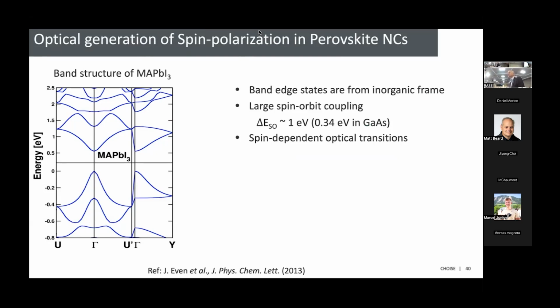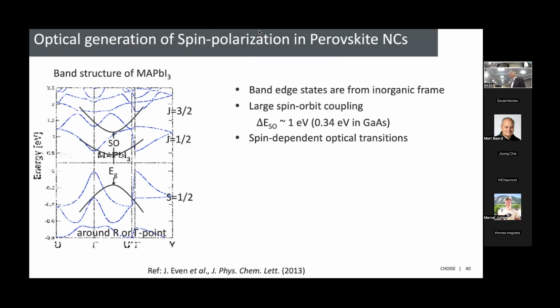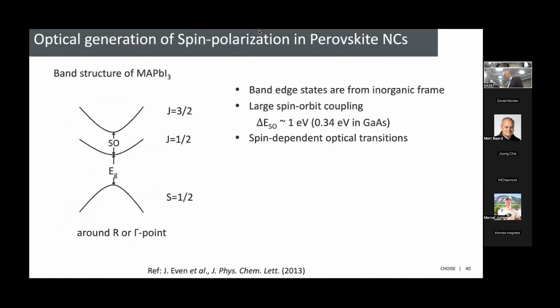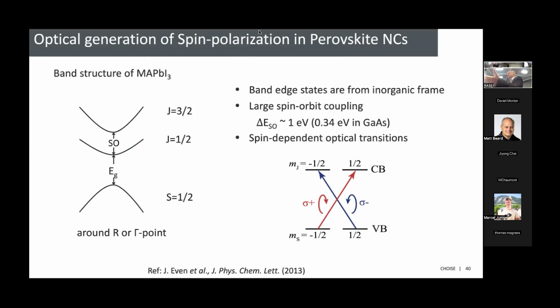And just to show you, here's the band structure of this guy over here at the band edge. You can think about this as just a two-level system down at the band edge, because the spin-orbit coupling pushes the other p states way high. You have J 1/2, S at 1/2 over here, and so you have these M sub J levels. If you shine circularly polarized light on this system, you can drive this transition, and that means you can optically generate spin polarized carriers with circularly polarized light.